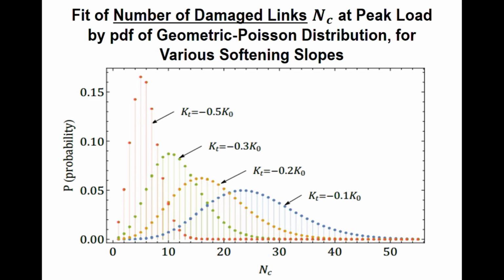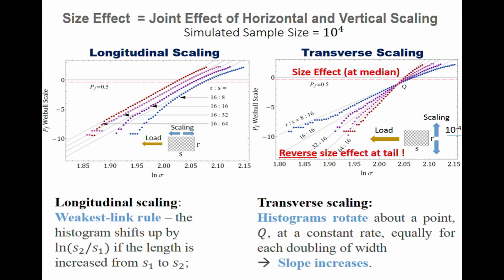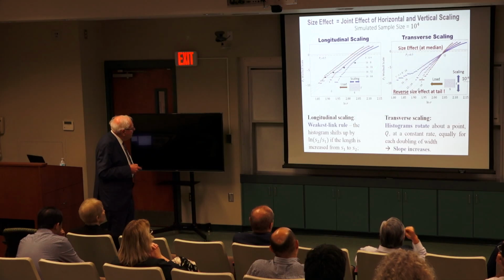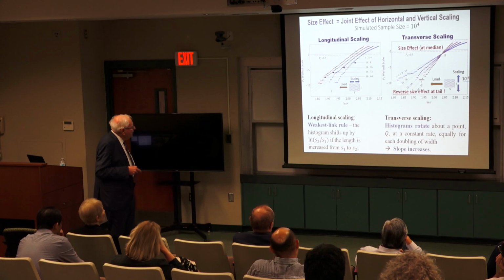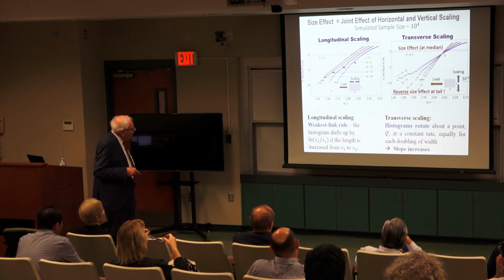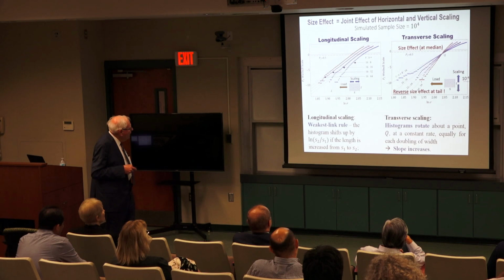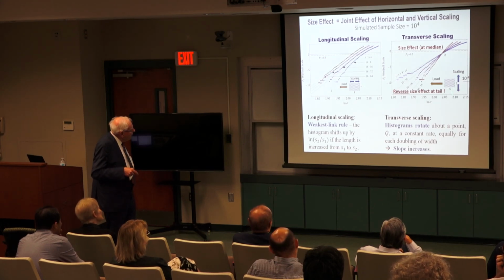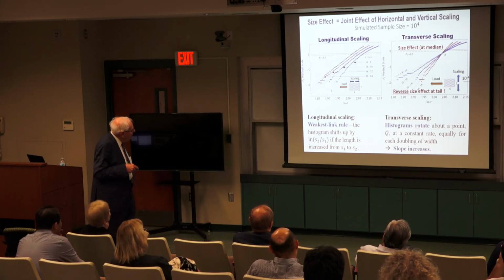And further comparisons for different slopes of the softening. Small slope here to big slope, different behavior. And how to determine size effect. Now from size effect you can go back to distribution. Now we found this very simple property. It is difficult to judge what if you enlarge geometrically the fishnet, enlarge both length and width in the same proportion, which is the definition of size effect. But we split it into two kinds, that we enlarge it longitudinally and here enlarge it laterally. Longitudinally, you see that in the middle you keep the same slope, same Weibull modulus, but deviates earlier.